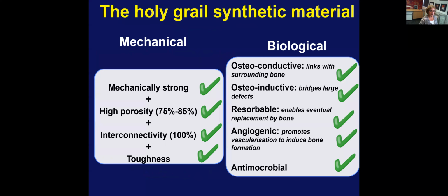The first project I'm going to talk about is the Holy Grail of synthetic material. I'd like to call it the Holy Grail because it has shown us that this material is mechanically strong at high porosity and interconnectivity. At times it can become tough. So this is a pure ceramic for regeneration of large bone defects under load. We have shown that this material is highly bioactive. We haven't confirmed the resorbability yet, but I'll show you evidence of some of that. And the antimicrobial properties is the subject of the work with Khan at RMIT, who presented just before me.